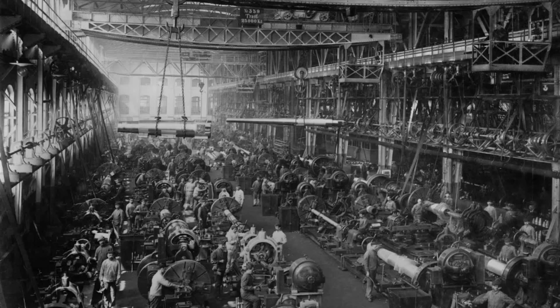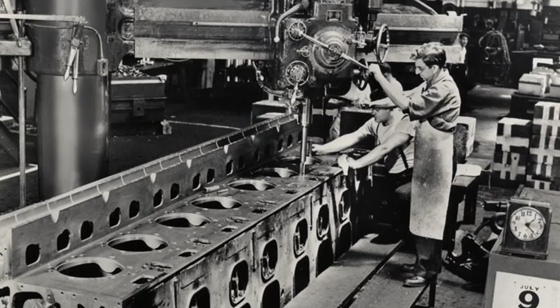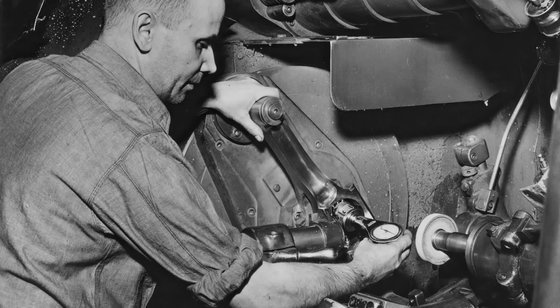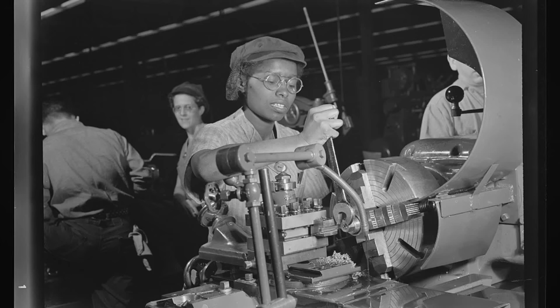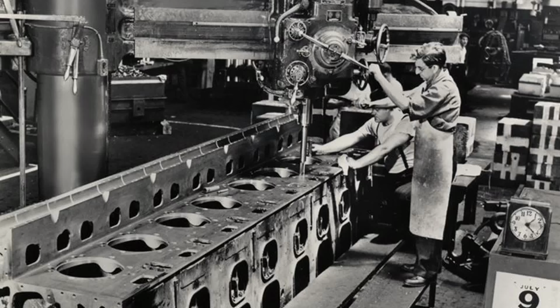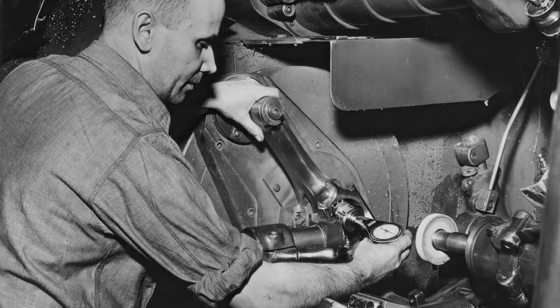Then the automobile industry gave carbide the opening it needed. By the early 1930s, automobile engineers were pushing materials and manufacturing processes in directions that created new machining problems. Brake drums provide a good example. Their inner friction surfaces needed consistent machining, but the cast iron could be abrasive and difficult on tools. Carbide could withstand the wear much better than conventional tooling. Another challenge came from aluminum pistons containing silicon. The alloy had useful properties for higher speed engines, but silicon particles made the material extremely abrasive to cutting tools. Again, carbide had an advantage.